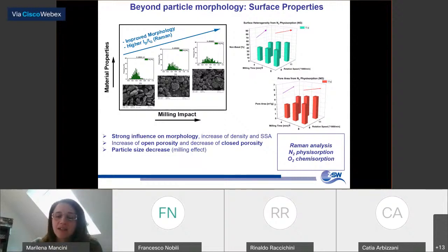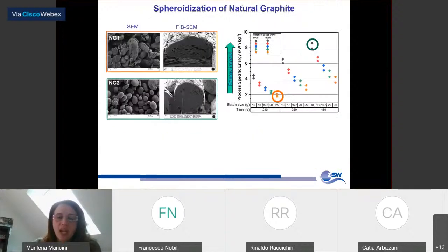And we have analyzed the particles from a large number of samples produced by several analytical techniques, including Raman, nitrogen physisorption, and oxygen chemisorption. So here I want to give you a short overview of some of the results obtained in this project. And here there is a scheme where I show you different process parameters and related products. We have selected for this study two materials produced with different conditions. As you see from the morphology, both materials have a potato-shaped morphology, so the spheroidization was successful.